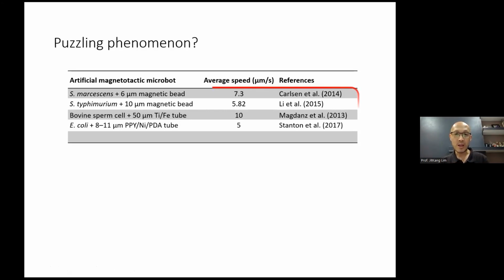And if you really look at all these studies, most of the average speeds reported so far are from a few micrometers per second up to about 10 micrometers per second. These speeds caught our attention because almost at the same time, we managed to track iron oxide magnetic nanoparticles, roughly 35 nanometers in size. That is way smaller than 6 micrometers or 10 micrometers. And the average speed achieved by these 35 nanometer iron oxide nanoparticles is roughly about 10 micrometers per second. So they're at the same order of magnitude, right?